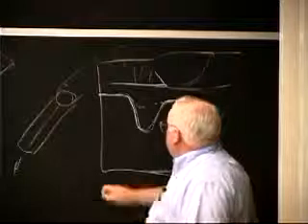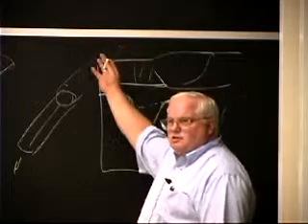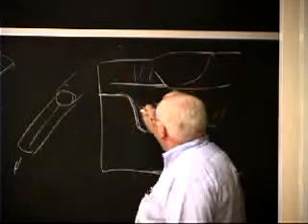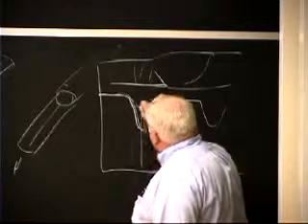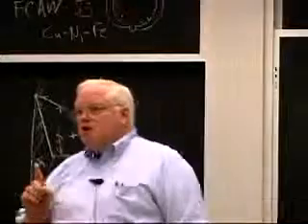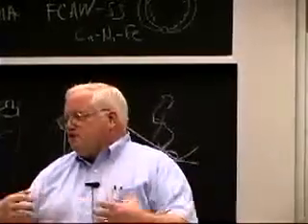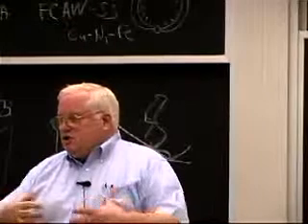And the reason was, this one actually had been pulled and work hardened in service. It had taken very high loads. I was able to measure that hardness, convert it to an approximate strength, and tell them what the maximum load had been on that structure over the previous 20 years. How far it had been stretched, what was the maximum extension, based on the work hardening.